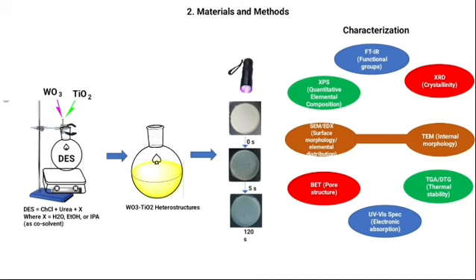The photochromic property of the as-prepared powdered materials that were collected after centrifuging and vacuum drying for 8 hours was studied by pressing the samples into a round groove and directly illuminating with a 300 watt xenon lamp, which was used as a light source at a wavelength and distance of 365 nanometers and 10 centimeters respectively, and all of this was carried out at room temperature. The coloration of the materials was monitored by measuring the UV absorbance at regular time intervals.